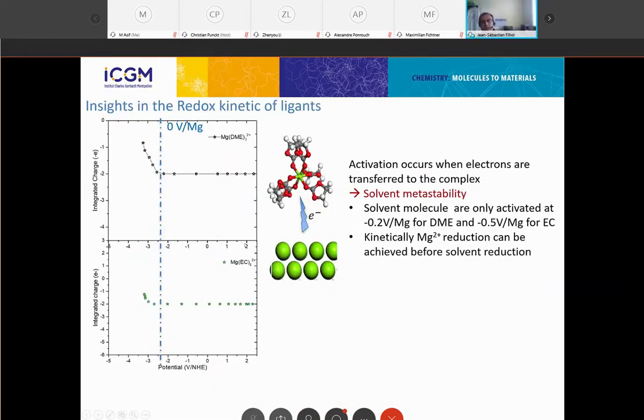Okay, so can we go a bit further on? We know that we have some metastability, but we want to get a more precise, more detailed range of this metastability, because we know that for many solvents, even in their metastability range, they can be used in electrochemistry. In this case, what we looked at is the total charge of our complex with the magnesium and the attached solvent around it, the first solvation shell. And with that, we look at the charge as a function of the potential. What we see is that we have a +2 charge most of the time. And at some point, an electron is transferred to the surface from the solvated Mg2+, and some reduction occurs. This can give us a first hint of where the electrochemistry is going to happen.